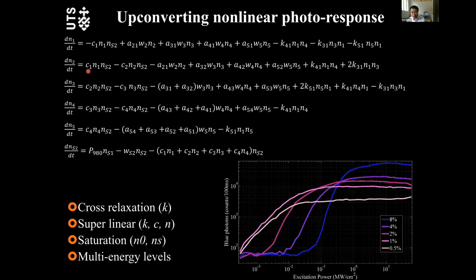Once you dope more emitters inside this material, you decrease the spacing between each of the emitters, and this will also change all of these constants. So which means the whole response is manipulatable. For example, in this figure, you can see that as we dope different concentrations, you can change the photon response curve. You can change it from the traditional 2-photon structure into a more-photon structure. Also, they look a little bit like an S-shaped curve because they also have the photon avalanche effect. And you will recognize it will also have some saturation.